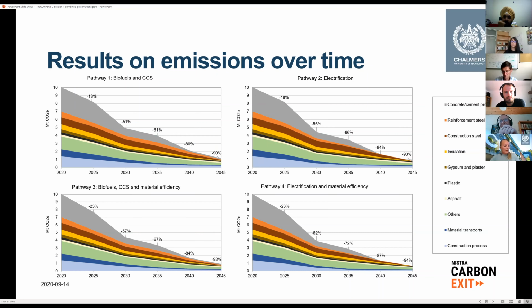In terms of emissions, we actually found in our modeling that all pathways have a potential to reach close to zero emissions in 2045, with emissions reductions ranging from 90 to 94%. And up until 2030, we see emissions reduction potential of over 50%. And as you can see, a lot of these stem from optimization of concrete.